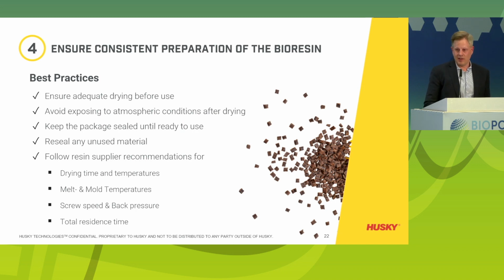Then the last point, point 4, is especially for molders. Always, as a molder, ensure that you use dry materials before you process. Avoid any exposure to atmospheric conditions after drying, so maybe use an on-machine hopper, or try to avoid any longer exposure to the atmospheric conditions. Keep the package sealed until it's ready to use. Reseal any unused material, and always important, follow the supplier recommendations on the drying time and temperatures, as well as melt and mold temperatures, screw speed, back pressure speed, and as well the total residence time. So that means the hot runner plus the machine is the total residence time.